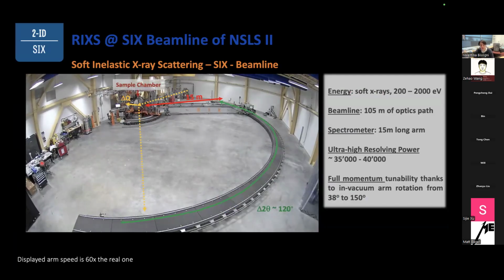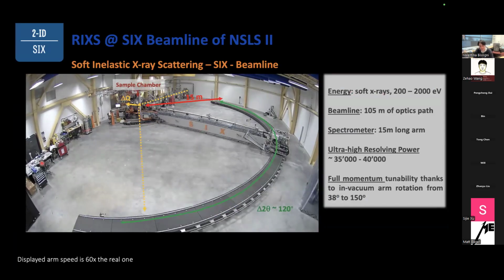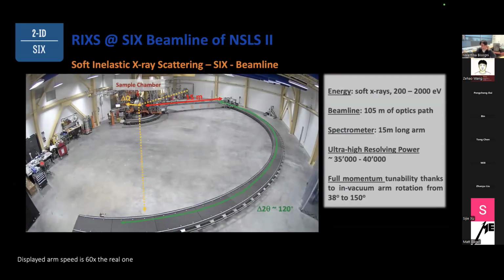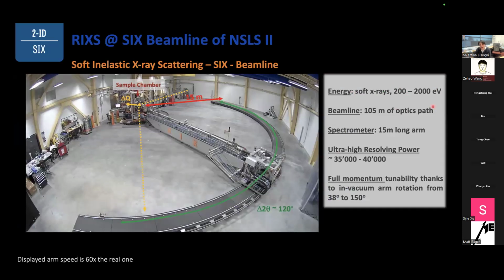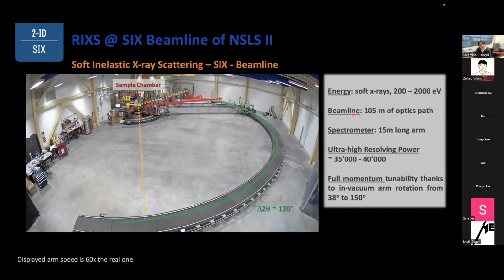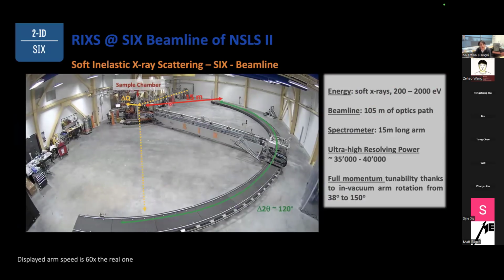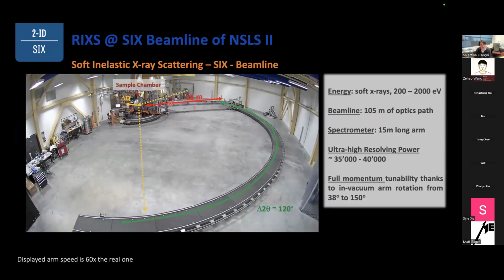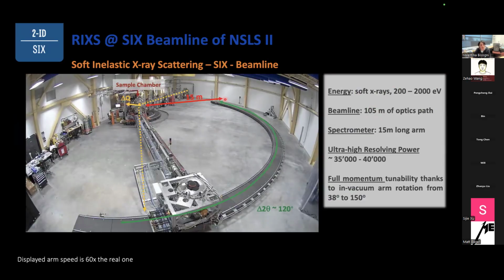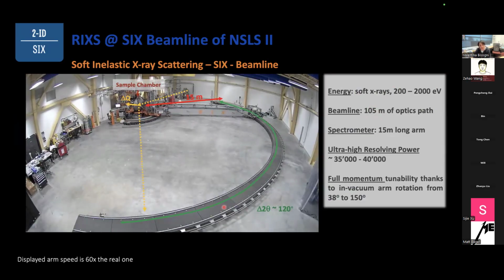Now onto the instrumentation that is required to realize this technique. I would say it is pretty spectacular and interesting. In order to perform RIXS with very high energy resolution, one needs extremely long beamlines, around 100 meters, and an extremely long spectrometer arm to analyze in energy the scattered X-rays from the sample. What I'm showing here is the SIX beamline that we have here at NSLS-II of Brookhaven National Lab, where we have this 15-meter spectrometer arm moving in the horizontal scattering plane.